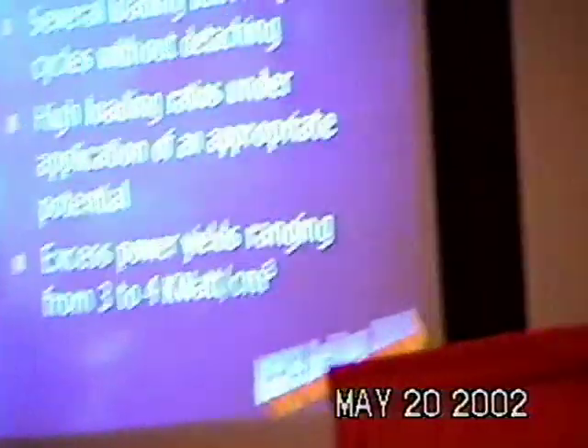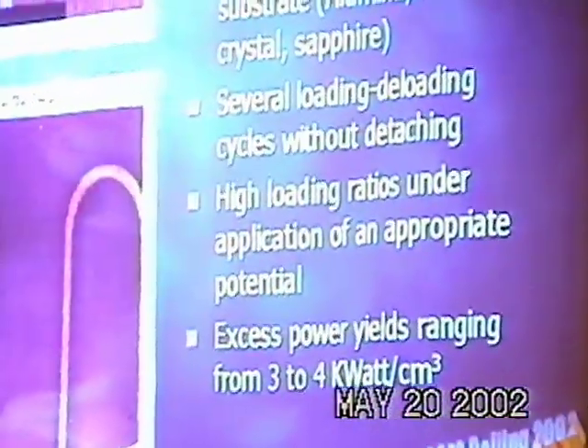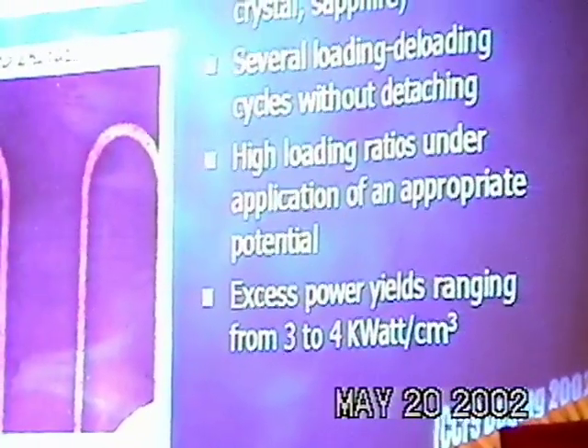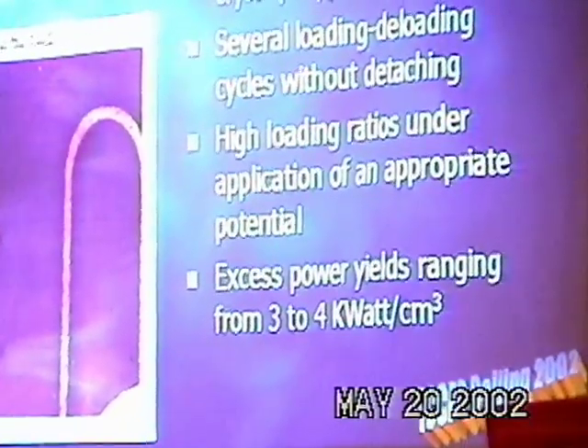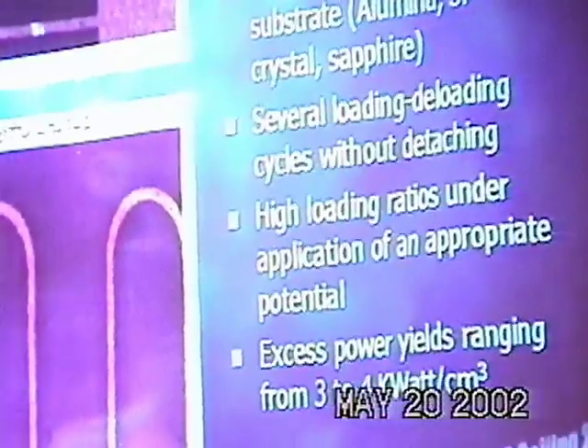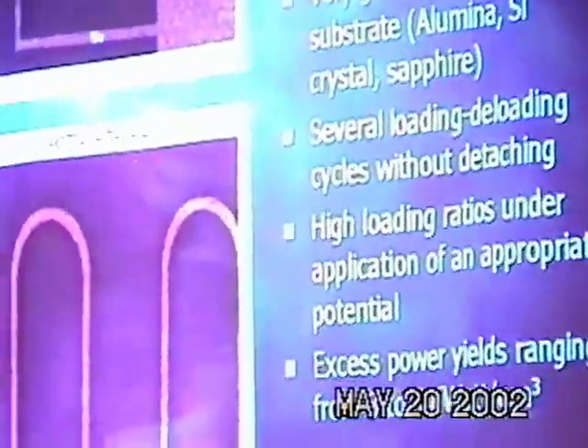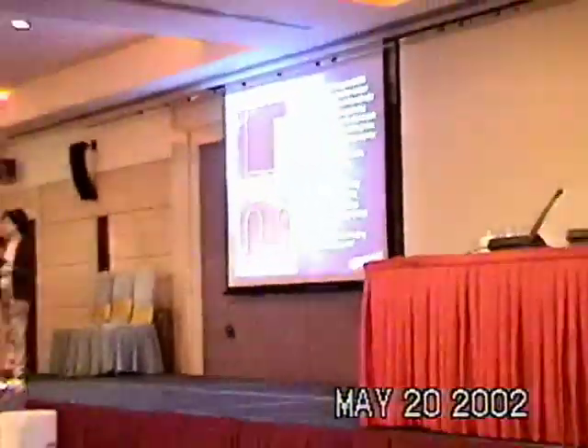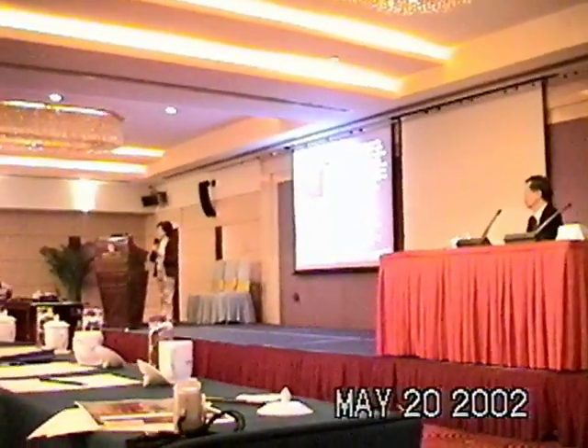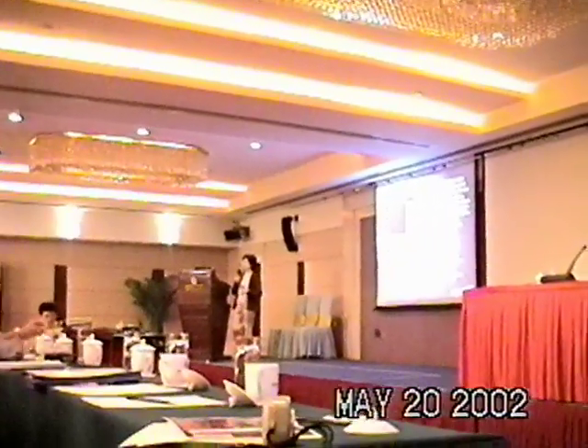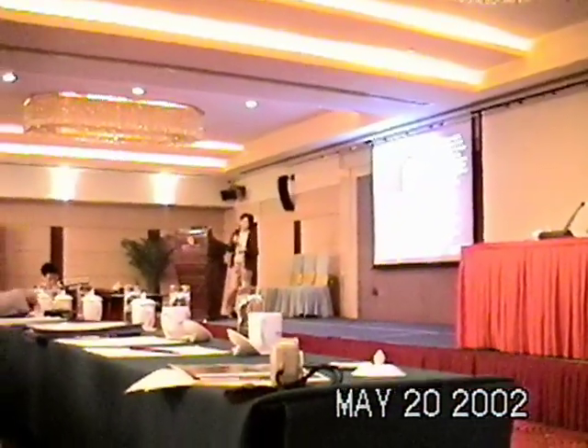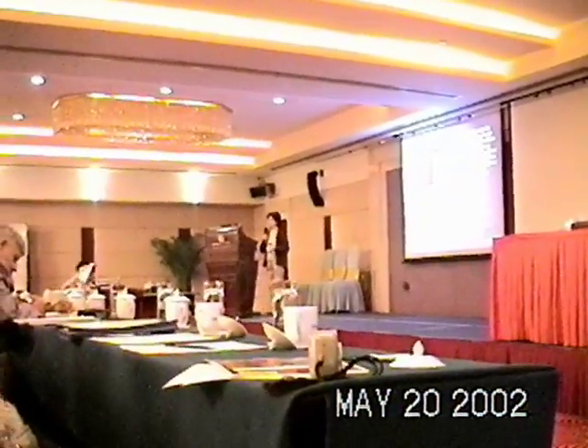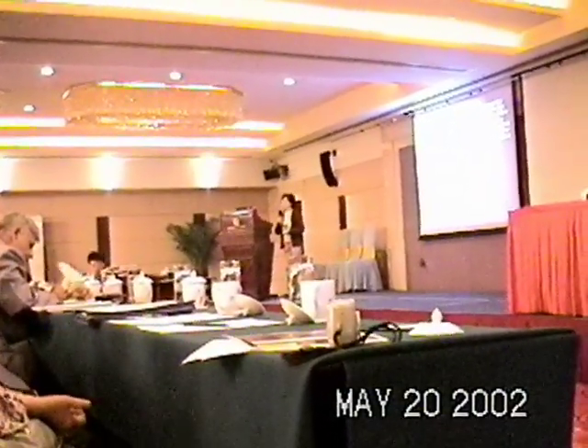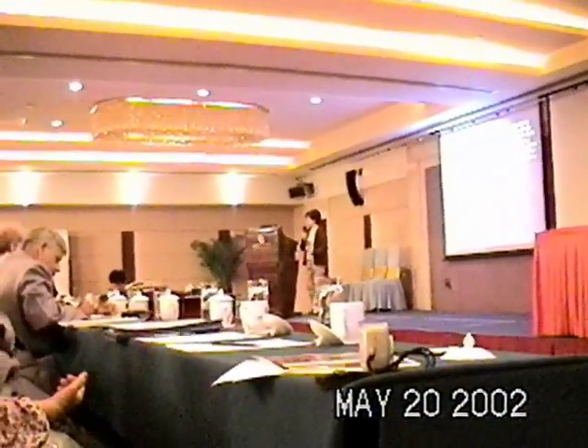So it's very difficult to convince the palladium film to stay on the substrate during the loading and eventually during the heat production. So we worked very hard on the production of thin films, and we found that we have to check every part of the process of production in order to obtain good results. It's very important, the selection of the substrate. We tested several substrates such as alumina, silicon crystal, sapphire, and the best result we obtained in terms of mechanical properties were obtained on alumina substrates.